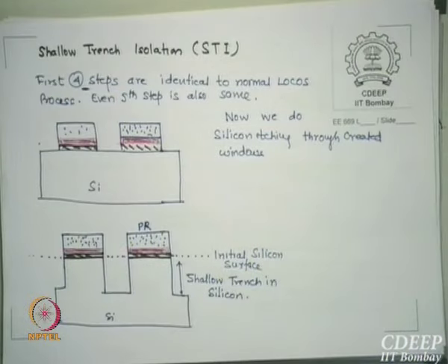First, I know HF etches silicon dioxide. So I must convert silicon into silicon dioxide. Nitric acid does that. 5-3-3 is the ratio: 5 water, 3 nitric acid, 3 HF. If I mix, or 5-3-1, depends on the company, plus water dilution if you want, 10% of this. These are called silicon etchants. Now this etchant oxidizes silicon and HF removes the oxides. But in this case, we will use only fluorine and fluorine ions to etch through.